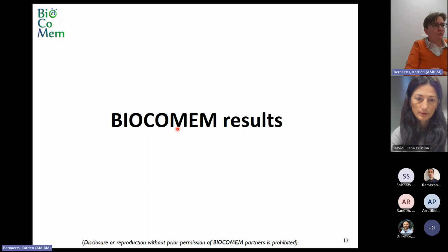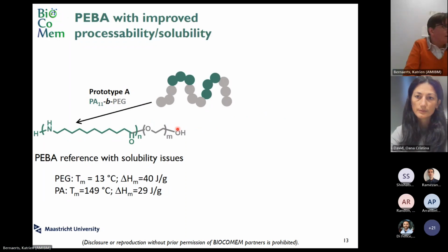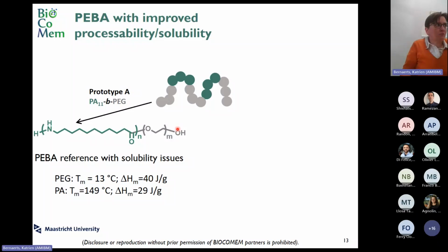After this introduction, I want to go to the results we obtained with Biocomem. As already mentioned, commercial PEBAs suffer from solubility and thus processability issues, but we are using them as a reference. We call it in our project prototype A. This is a commercial PEBA based on polyamide 11 and polyethylene oxide. It has a melting point of the PEG around 13 degrees and a melting point of the polyamide around 149 degrees. So our approach to improve the solubility is to decrease the crystallinity of the polyamide block.